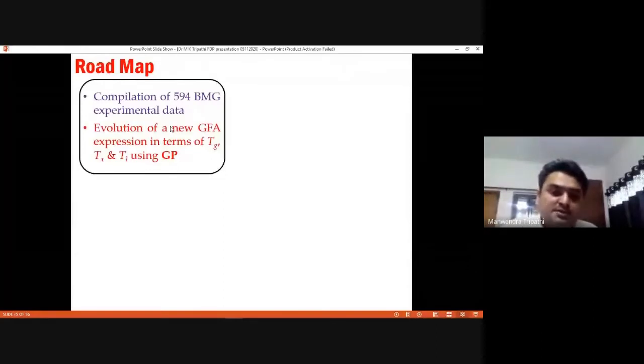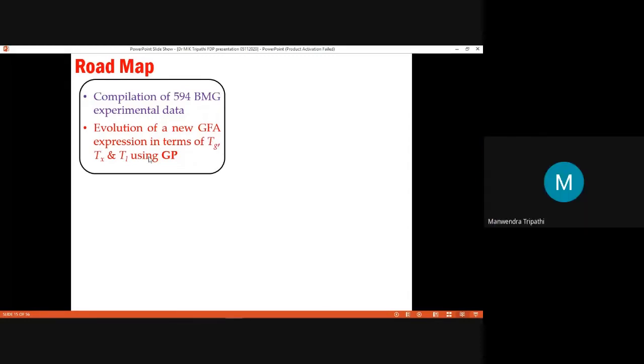This is our purpose. So for one experiment we have done, we have evolved a new GFA expression, okay, and that GFA expression is in terms of TG, that is glass transition temperature, and then TX is the crystallization temperature, and TL is the melting temperature, right? And we can experimentally determine this by DSC or DTA. If you are going to melt it, the lowest temperature is TG, below which it remains glass, above which it becomes liquid. And TX is higher than TG, okay? TX is the temperature at which it becomes crystallized, and TL at which it is going to completely melt. So you know that we are going to capture glass forming ability of an alloy in terms of TG, TX, TL using genetic programming code.